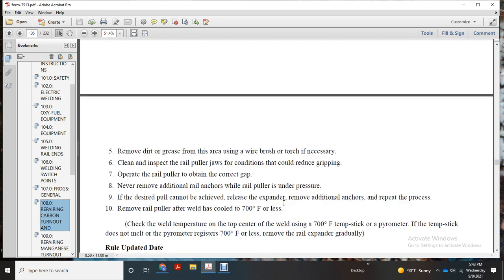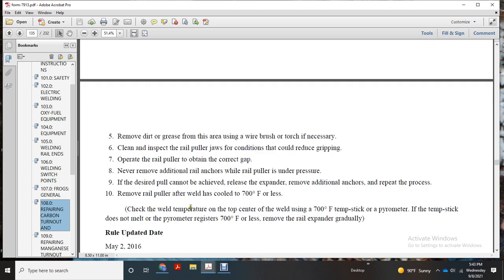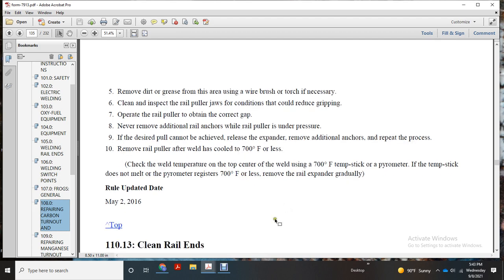Remove dirt and grease from the area with a wire brush or torch, and once it is clean, inspect the rail puller jaws for conditions that can reduce gripping. Operate the rail puller to obtain the correct gap. Never remove additional rail anchors while the rail puller is under pressure. If the desired pull cannot be achieved, release the expander, remove additional anchors, and repeat the process. Remove the rail puller after the weld has cooled to 700 degrees Fahrenheit or less. Check the welding temperature of the top of the weld using a 700 degree Fahrenheit temp stick or pyrometer. If the temp stick does not melt or the pyrometer registers 700 degrees Fahrenheit or less, remove the rail expander gradually.